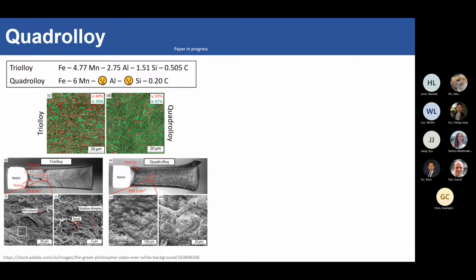So after many sad times, we went back to the drawing board, and now we've developed a new alloy, which is Quadrolloy, which is the fourth alloy. Yes, correct. So in the Quadrolloy sample, we've actually decreased the carbon content significantly. We've gone from 0.5 and now we've gone down to 0.2. So this is a reasonable carbon content that's actually weldable. So Quadrolloy, we've sent off to the University of Alabama for spot welding trials. So we look forward to their results.